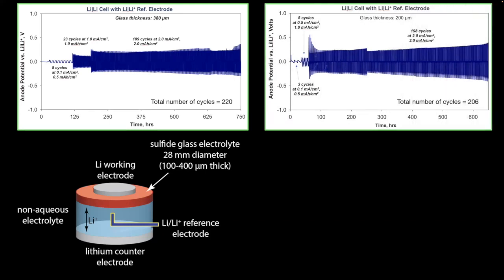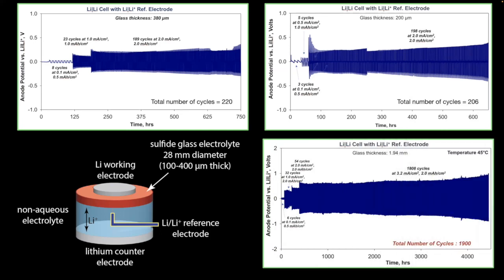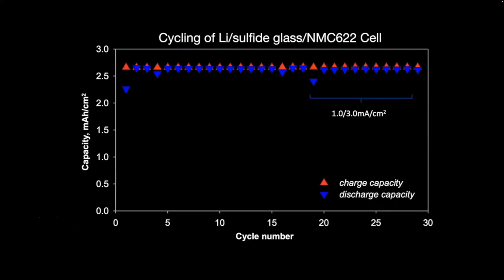And we can also, of course, test at warmer temperatures. That's room temperature here. We're at 45 C and we get about 2000 cycles as we cycle these materials. And of course, we build full cells. You can see here, we're cycling against NMC 622. We see good capacity retention, cycling at roughly C rate, commercial capacity. So these are behaving well.